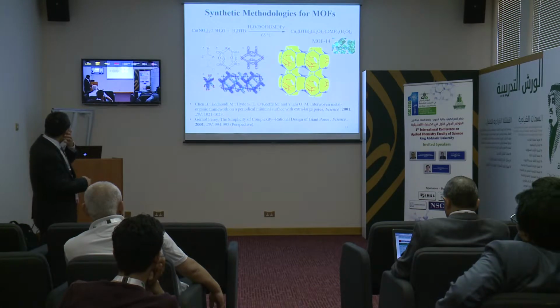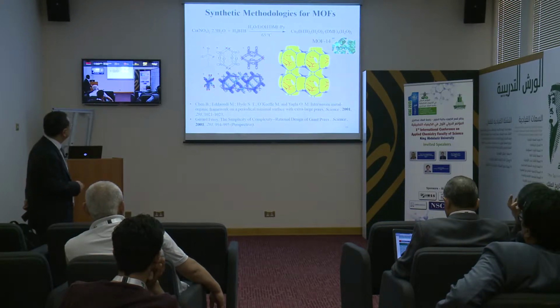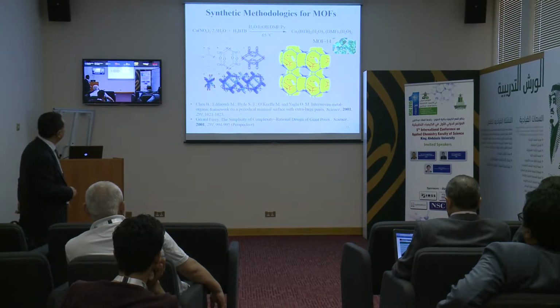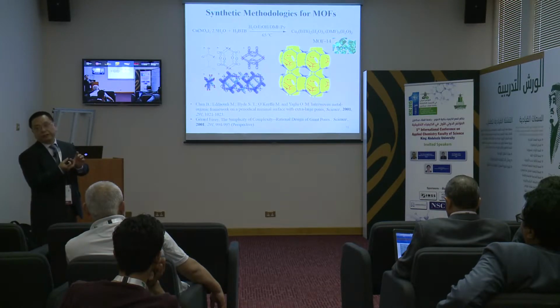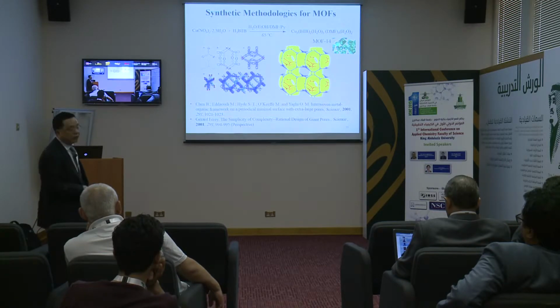And so I worked with Omar, and we used a very simple synthesis approach, the solvothermal approach. Before this work, the original MOF-5 was a little bit complicated to synthesize by the diffusion technique, which takes a while. So this solvothermal method is very simple, and we can synthesize the material typically within 1 day and get a very nice crystal. Also, a large linker can be incorporated into the MOF material. This linker is kind of large, so the framework has been interweaving. Basically, it's two identical frameworks interweaving with each other, but it is still porous. So Mohammed also helped to establish the permanent porosity.